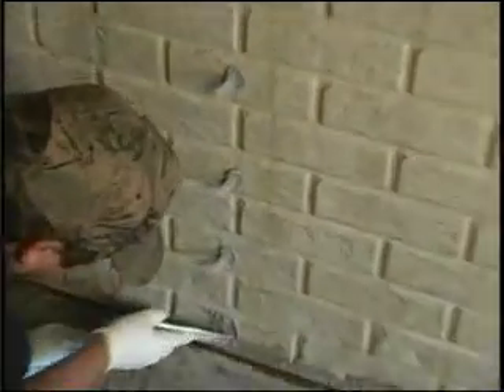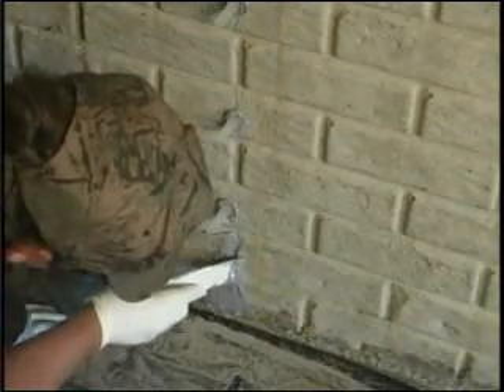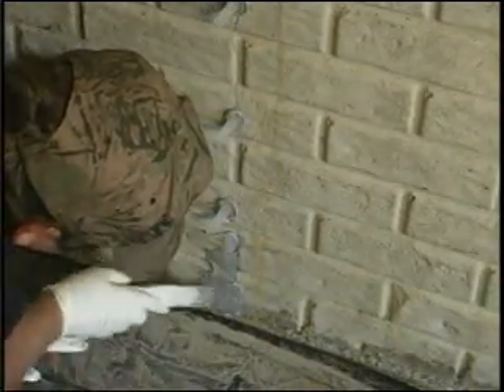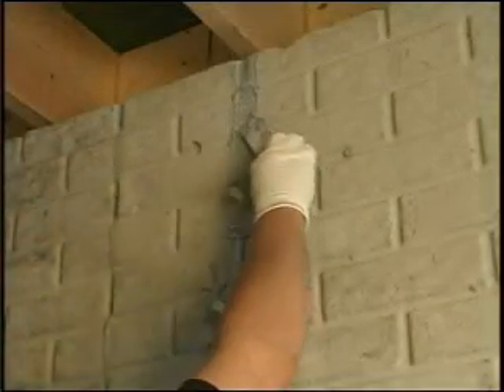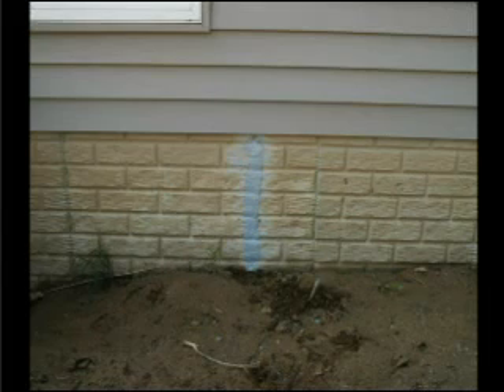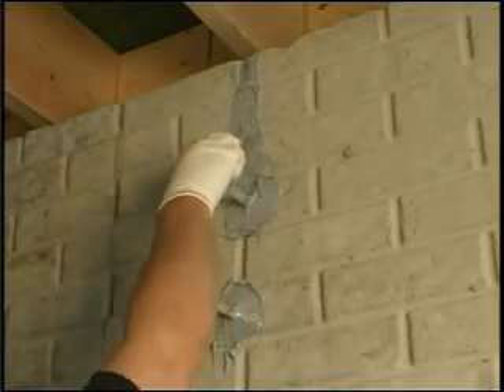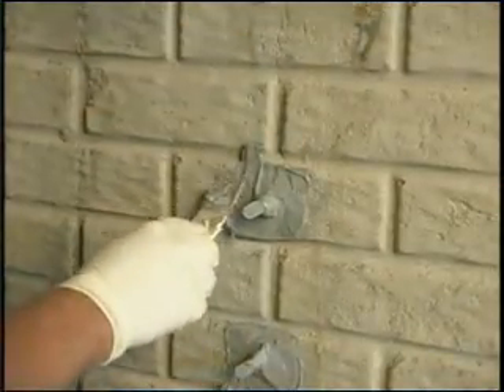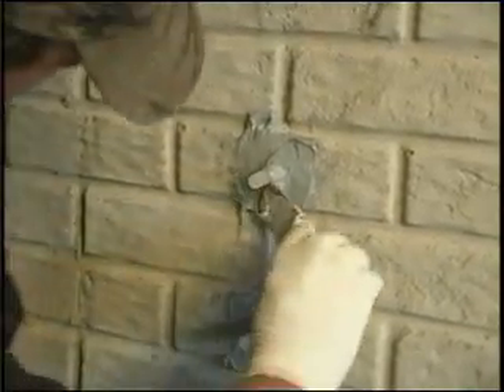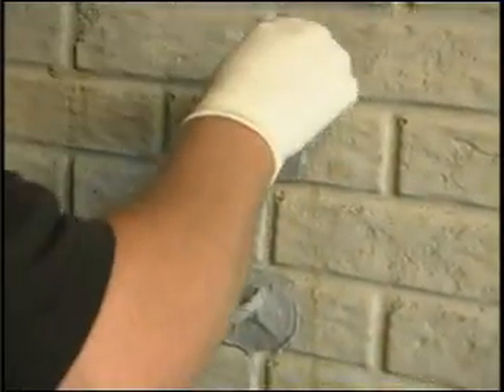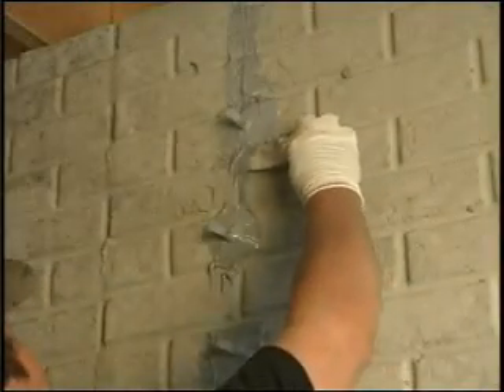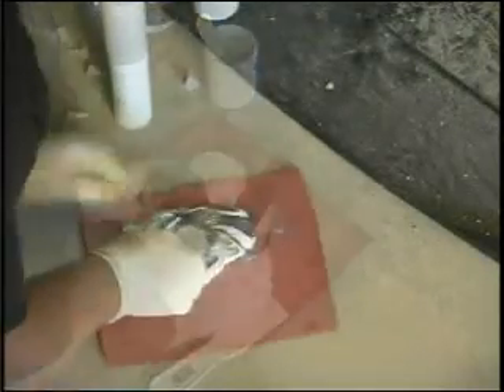The next step is to work the mixed surface seal epoxy paste along the entire length of the crack using the plastic trowel. If the crack goes to the top of the wall, you will need to apply a layer of sealer above the soil grade on the outside of the foundation as shown here. The recommended epoxy application is 1/8 inch thick and 2 inches wide. Make sure to apply sufficient amount of extra epoxy around the base of the ports. Do not work the epoxy into the crack, just paste over the surface. Expect to use 16 ounces, the total amount provided for an 8-foot crack.